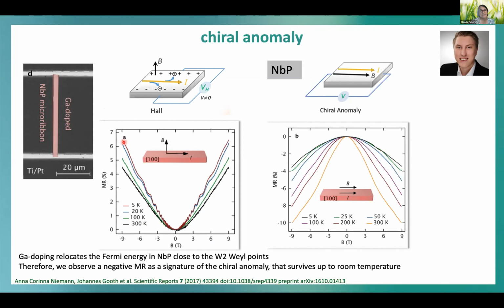This we can investigate, because here you see the measurement of the magnetoresistance in a field, and it's a positive magnetoresistance. And you see these wiggles here, which are quantum oscillations of the material. From the quantum oscillations, we can conclude the Fermi energy, so we exactly know where the Weyl points are and what the electronic structure is.